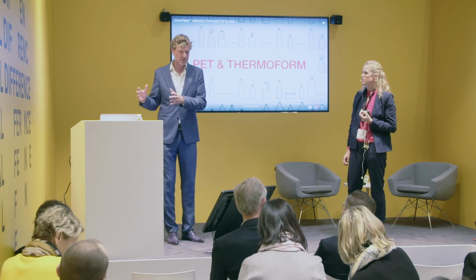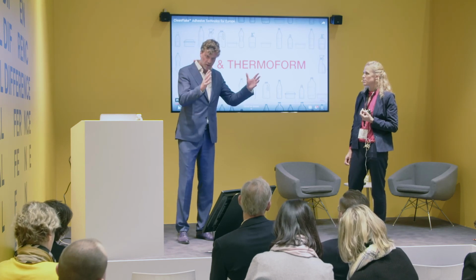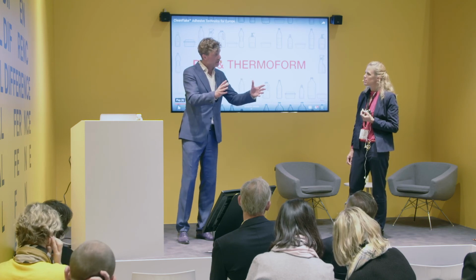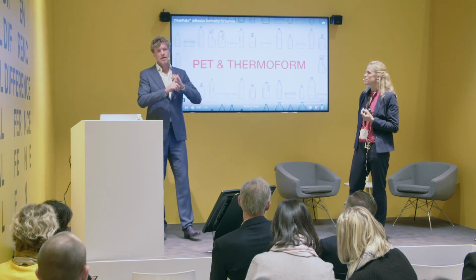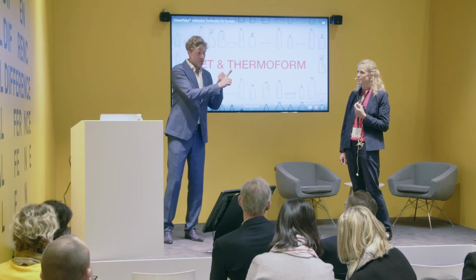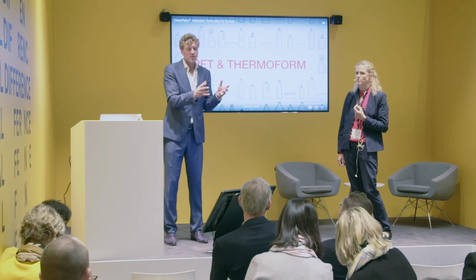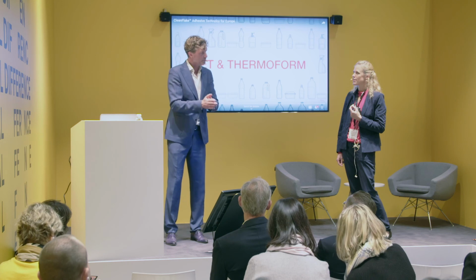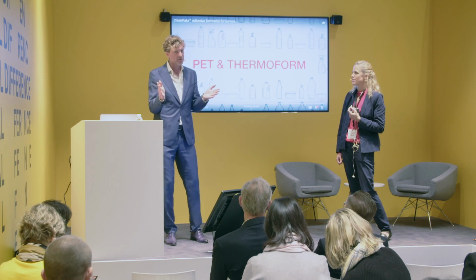If you look at chemical recycling, just as the current mechanical recyclers, also chemical recyclers are dedicatedly working on one type of material. So we have Ioniqa now having a first plant in the Netherlands on the depolymerization of PET. So if you put a PET bottle in there, like the one I've shown previously, with the LDPE wrap around it and the PE cap, actually, first we still have to do the sorting step because they want a high yield. So you cannot just throw every packaging in there. So the first step still needs to be done. So we need to be able to identify it as a PET bottle. And when it goes there, everything that's on there, which is not PET, will actually be discarded as well. They're only looking for the PET.